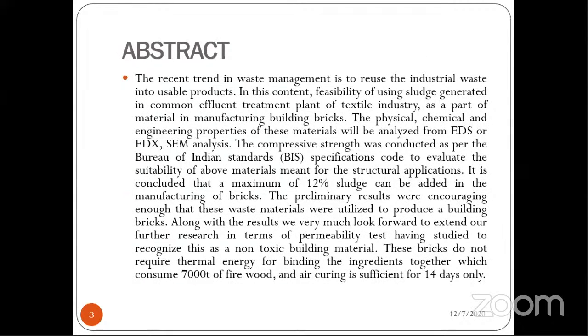The recent trend in waste management is to reuse the industrial waste into usable products. Sludge is generated in the common effluent treatment plant of textile industry. The physical, chemical, and engineering properties of this material will be analyzed from EDS or EDX and some other analysis. The compressive strength was tested as per Bureau of Indian Standards to evaluate the suitability of the material in structural application. It is concluded that a maximum of 12% of sludge can be added in the bricks.